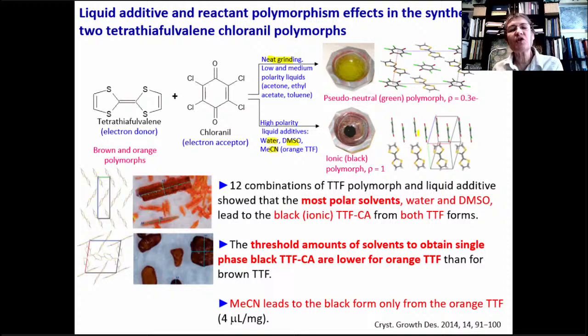So it was also observed that the threshold amounts of solvents that were necessary to obtain single phases of the ionic form were lower for the orange TTF than for the brown TTF. So the reactant polymorphism had also an effect toward producing these two polymorphs of the charge-transfer complex. And acetonitrile only led to the black ionic form from the orange tetrathiafulvalene.